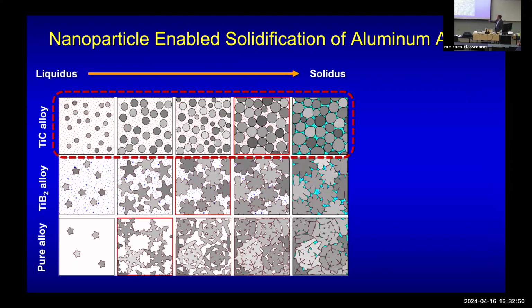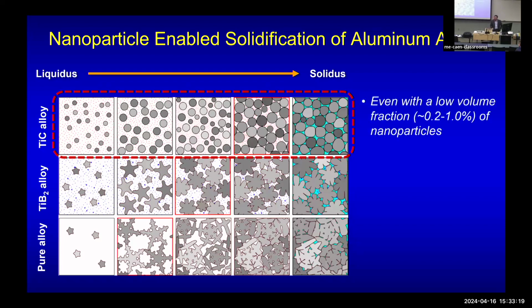So with nanoparticles, for example, here we always have equiaxed, also globular grains, and then they always grow very slowly, gradually. So their solidification zone, like a latent heat zone, is a little longer than columnar because the nuclei grow slower, allowing us, during the latent state, a much longer time for liquid to penetrate and backfeed. So in this way, we can really solve the problem, even with a low percentage, and that's good for industry guys, right? So lower cost, lower percentage, better economics.